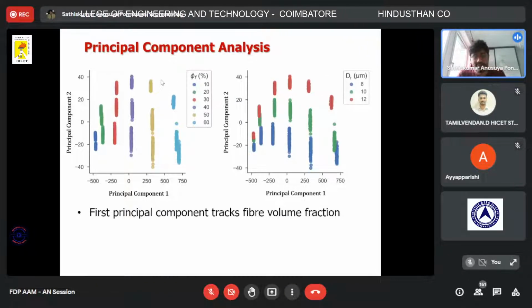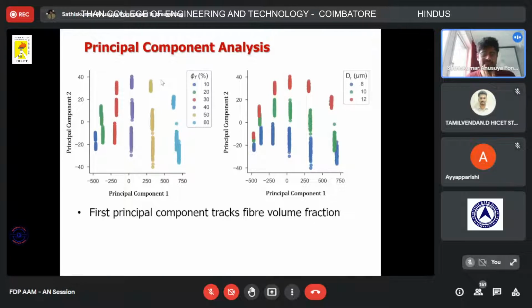And the beauty here is that representing a system using its eigenvalues is much more efficient, because it captures all the ingredients with a limited number of numbers basically. So what you see here, I plotted the principal component 1 versus 2, and on the left you see different islands of dots, different colored dots. Each of them is clustered by itself according to the volume fractions and according to the fiber diameters, as you see on the right. Which means these principal components actually capture the necessary details in the microstructure. It does not lose anything.